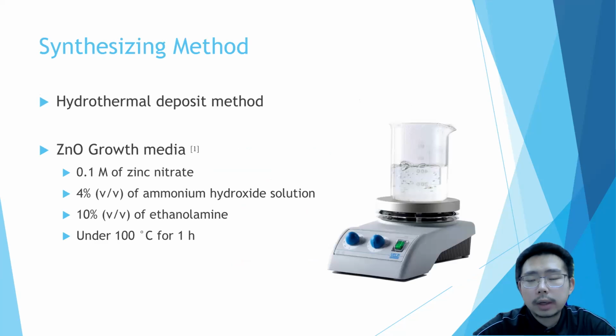So for the synthesizing method, I'll be using hydrothermal deposit method, and the setup is very convenient. Similar to this picture on the right, I'll be using a hot plate with a beaker on top of it. The zinc oxide growth media recipe was taken from a published paper, and the temperature was changed from 140 Celsius to under 100 degrees Celsius. Temperature was changed because of the material property of the 3D printed resin. If it is under higher temperature, it could deform or even melt.